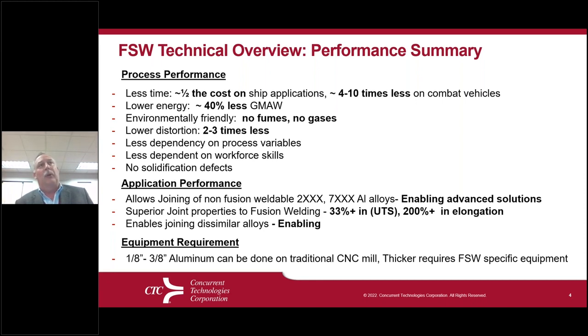This is not just in aluminums. This could be applied to coppers, titaniums, stainless steels, and so forth. But in the aluminums, the joint efficiency is typically much higher than a fusion weld, upwards of 33% higher strength in ultimate tensile strength of the welded joint. And we can see elongation improvements up to 200% over fusion welding.